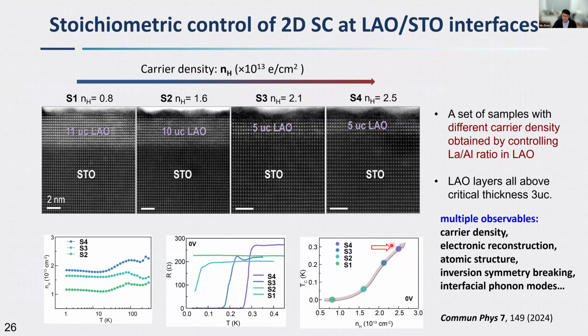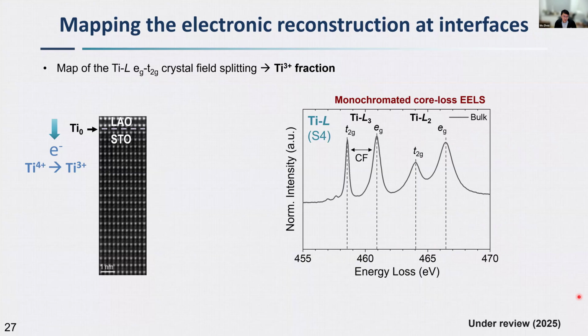So we'll use these four samples to look at several variables. One is the charge carrier density, and the other is the electronic reconstruction at the two-dimensional electron gas, and then correlate it with the structural symmetry breaking and the interfacial phonon modes. All quickly done on the same microscope during the same experiment. So first we look at the electronic reconstruction introduced by the 2D electron gas.